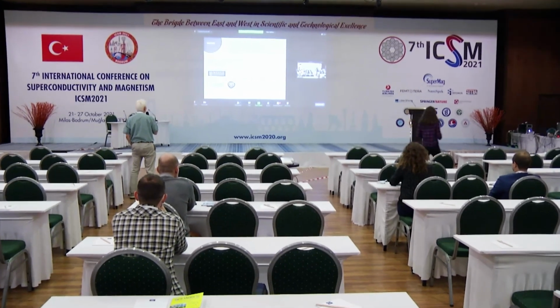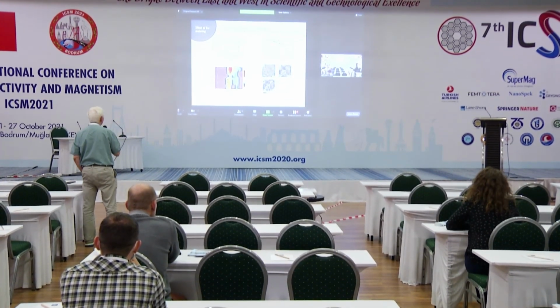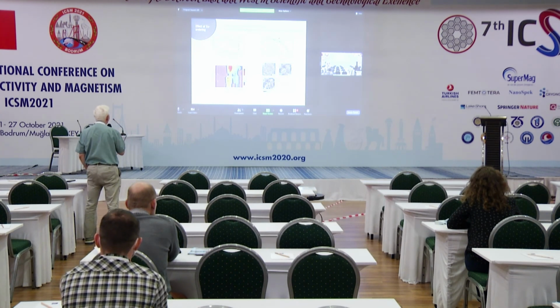May I ask a question? On page 12, you showed the optical reflectivity versus temperature, and you interpret this flattening marked with the red arrow. You said that the superconductivity weakens at this temperature, and this might be an effect of the TM. But in fact, there could be a different interpretation, since you know the values of the 2 or 3 gaps in this material. You could fit the data using the multi-band model.